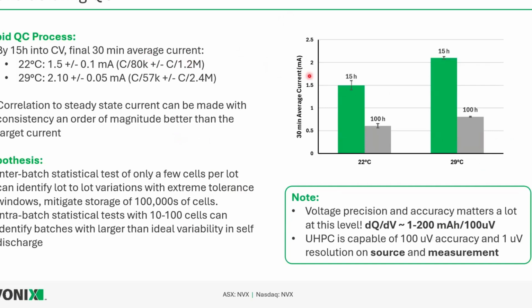So this is just another way of looking at those data to show that at the level we're looking at, in only 15 hours, we're very accurately able to measure the differences between these cells. And there should be a path to making QC happen, not just in this 100-hour CV hold, but even in just a few hours, less than a day, using UHPC. And again, it's really important to consider that this has as much to do with the current accuracy and precision as it does the voltage accuracy and precision in actually holding the cell at that voltage to keep that current steady.